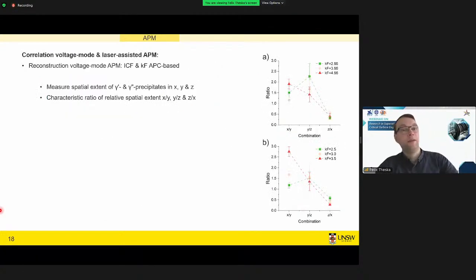Okay, let's move on to the reconstruction parameter calibration. And what this slide is showing you is basically how we use the precipitate morphology. So we start with a voltage mode data set where we can see these gamma prime, gamma double prime precipitates. They have a certain shape, extent in X, Y, and Z. And then we can give the relative spatial extent of X, Y, and Z to each other. And as we play around with the reconstruction parameters, we see that we can either stretch or compress these particles. And because it's the voltage mode calibrated data, we know what is the correct shape of these particles.